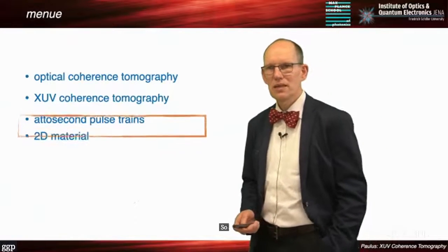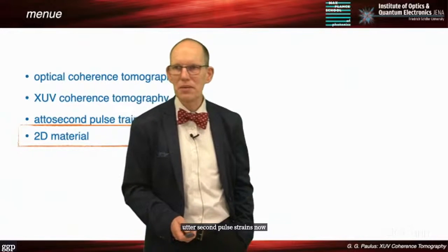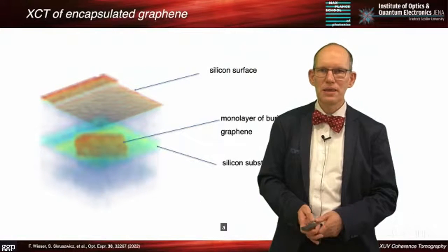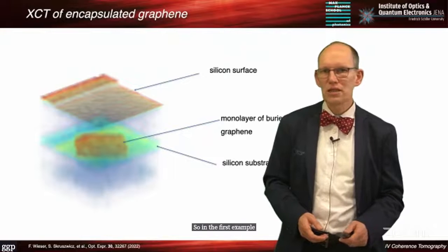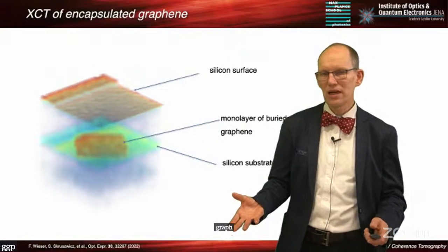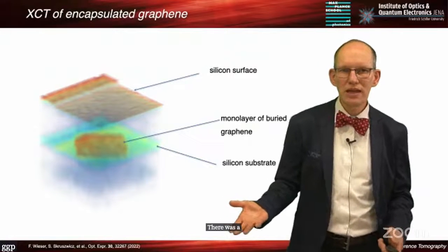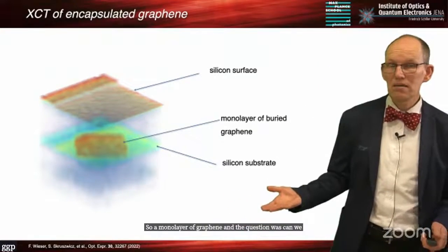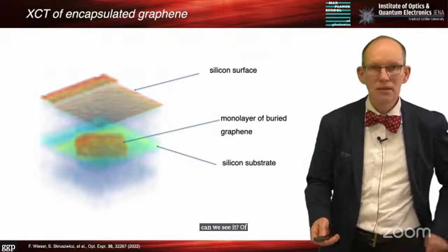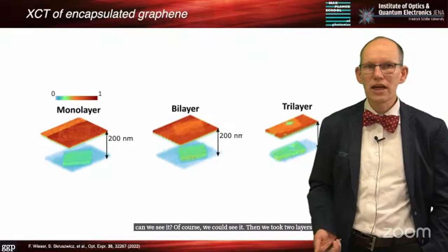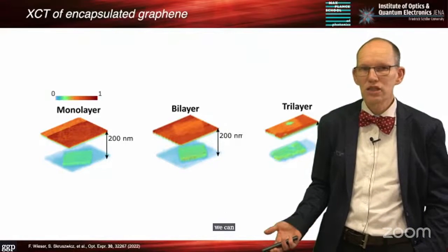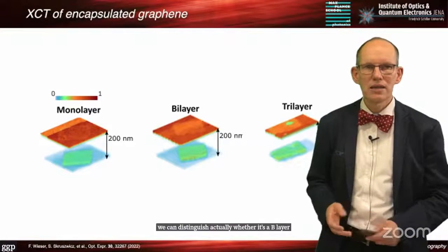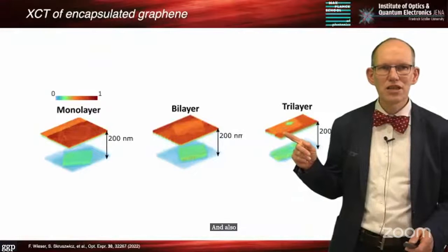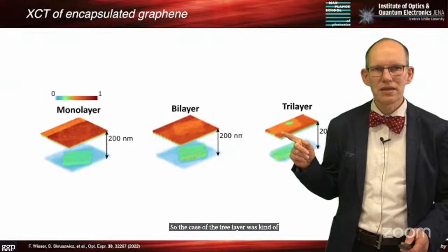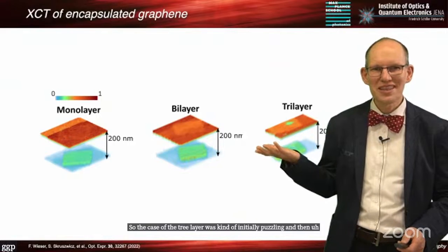So this was attosecond pulse trains. Now a few more examples, namely 2D materials, was also a series of works that we did. In the first example, we just buried graphene into silicon. A monolayer of graphene, and the question was, can we see it? Of course, we could see it. Then we took 2 layers, and 3 layers, and we can distinguish whether it's a 2 layer or a 3 layer. The case of the 3 layer was initially puzzling, and then after you have solved it, it's of course interesting.